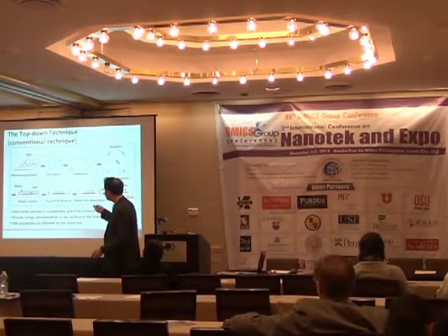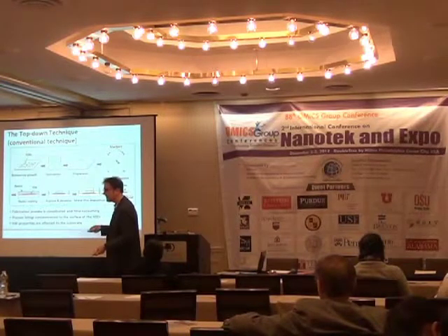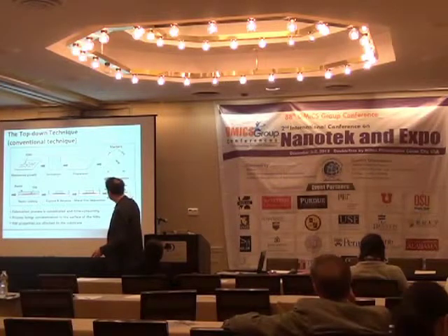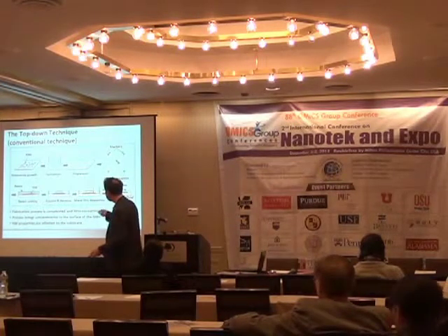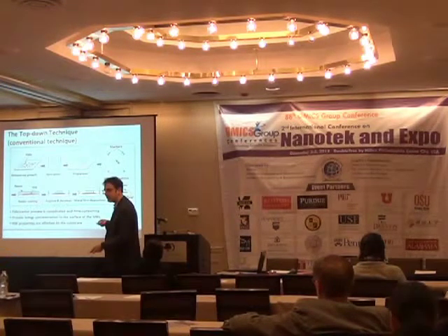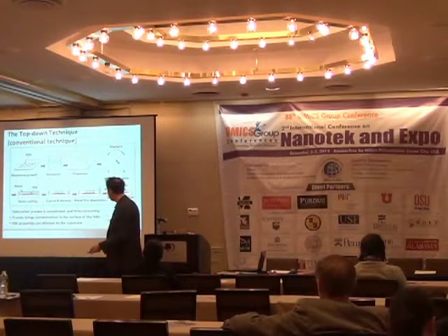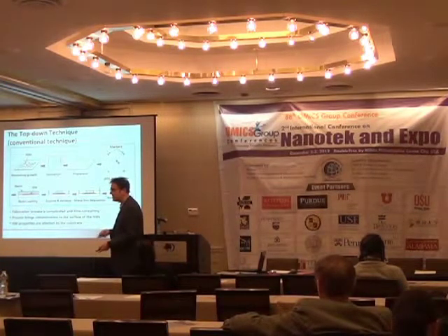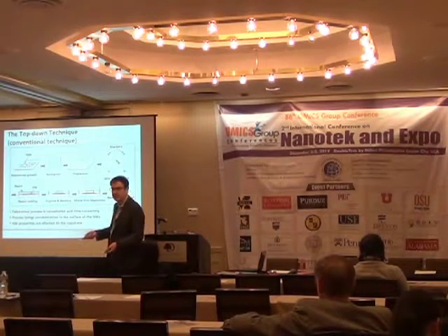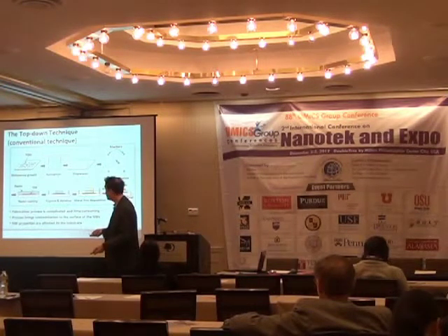That shows the standard top-down technique that is used in the laboratory to make the detectors. You start with messy nanowires, disperse them, put them on a surface, then look for the nanowires, make marks, and then use this process here to fabricate two electrodes. And then you have your detector. This is a single nanowire detector. It's very interesting because it allows you to get the fundamental properties of the nanowires, but it's not very practical as a means to make a sensor. A lot of steps.